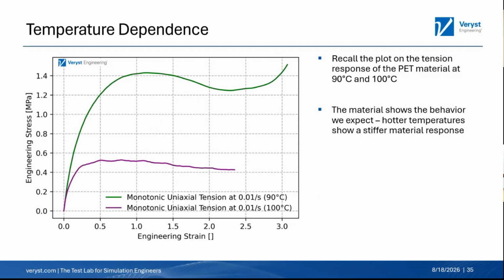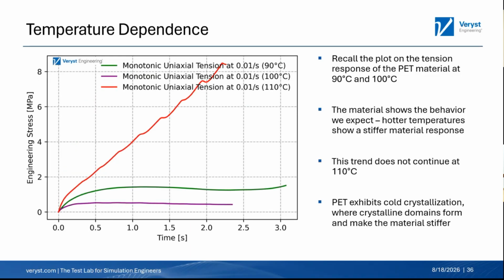What we're going to see is that as we go to higher temperatures, we might not always get the trend that we expect. So here at 90 C, we have a stiffer material. At 100 C, it drops pretty significantly, a factor of 2 or 3. And then you'd expect the same thing to happen at 110 C. But this red curve is what happens when we do that same PET material at 110 C. Now that's a much stiffer response, right? Even at small strain, maybe 2x the stiffness or the strength of the other materials.